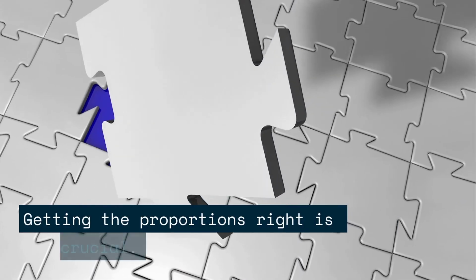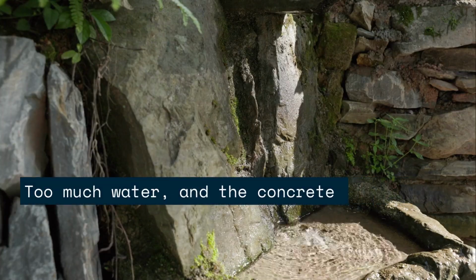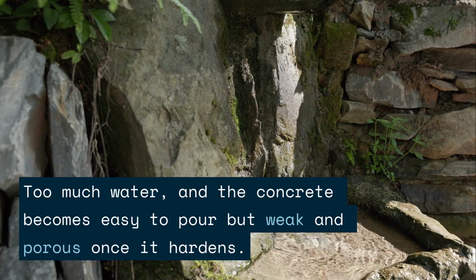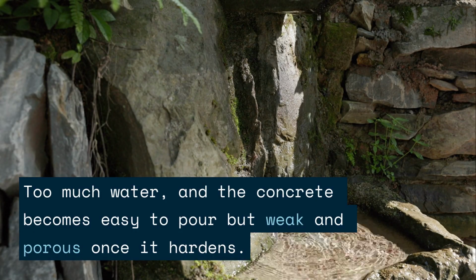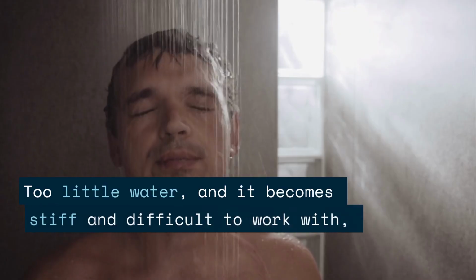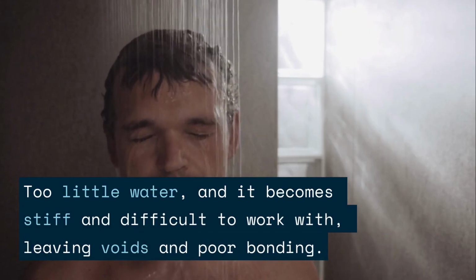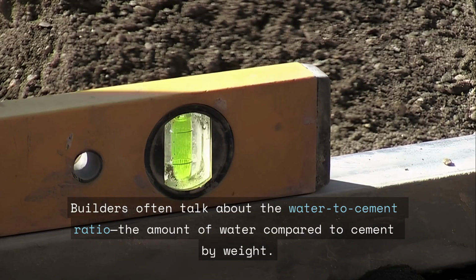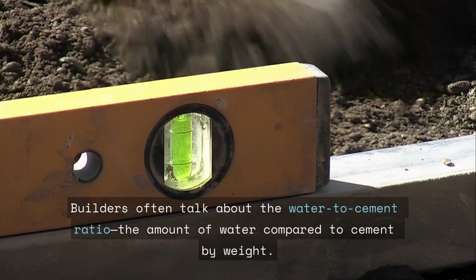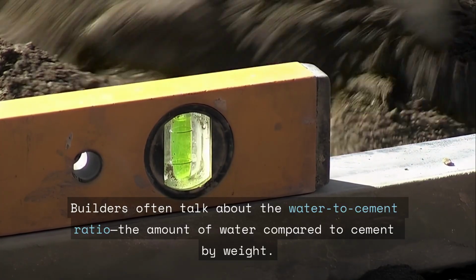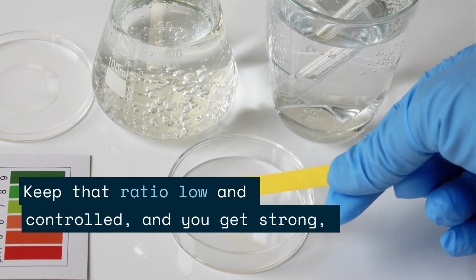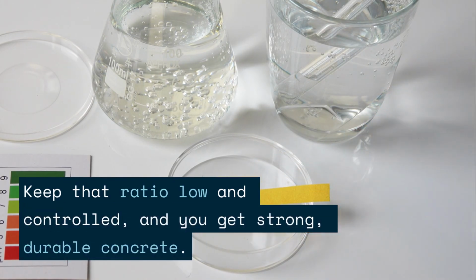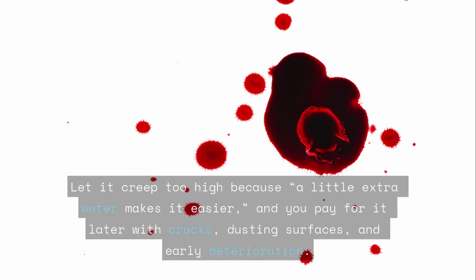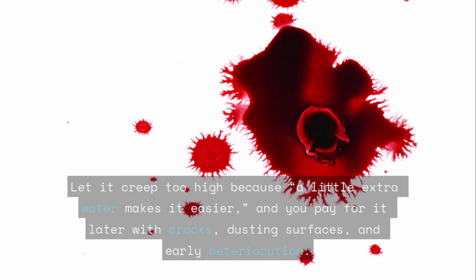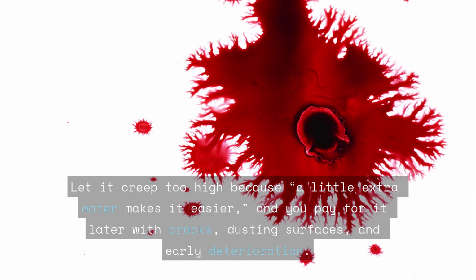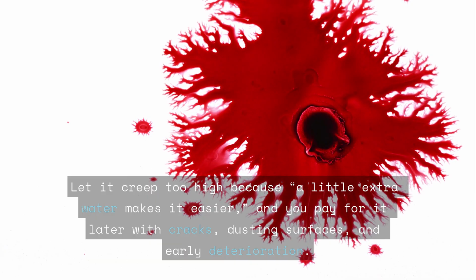Getting the proportions right is crucial. Too much water, and the concrete becomes easy to pour, but weak and porous once it hardens. Too little water, and it becomes stiff and difficult to work with, leaving voids and poor bonding. Builders often talk about the water-to-cement ratio, the amount of water compared to cement by weight. Keep that ratio low and controlled, and you get strong, durable concrete. Let it creep too high because a little extra water makes it easier, and you pay for it later with cracks, dusting surfaces, and early deterioration.